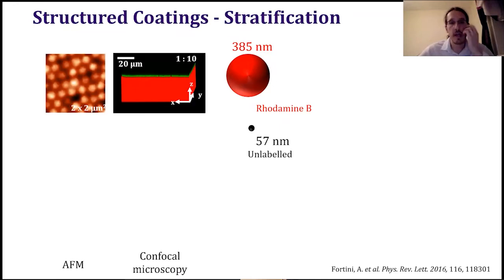So you can see that when we have only a few small particles, only 10 small particles for each large one, the top surface just shows that we have just large particles, and also if we look inside, we can see that the distribution of large particles is very homogeneous in height. It barely changes. Just to comment, the green is just the marker of the top surface. It doesn't mean that it's a different particle.